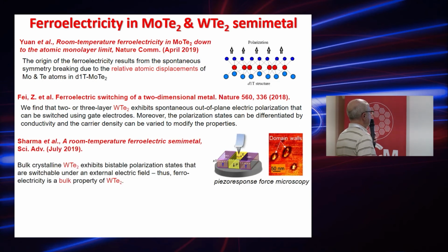These 2 papers investigate monolayers and few layers samples, and Sharma investigated bulk samples of tungsten ditelluride with the title "A Room Temperature Ferroelectric Semi-Metal," and they concluded that bulk crystalline tungsten ditelluride exhibits stable polarization states that are switchable under the external electric field. Thus, ferroelectricity is a bulk property of tungsten ditelluride.